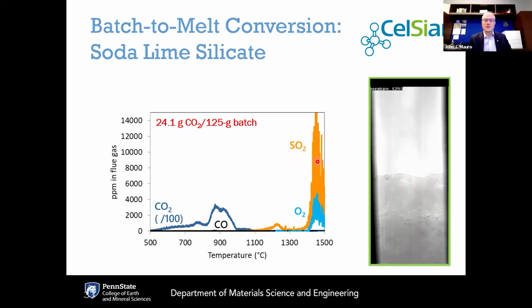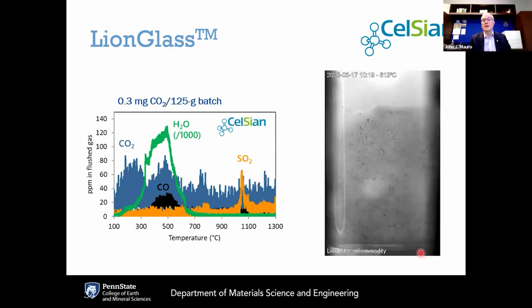The SO2 blisters are just because sodium sulfate is being used as a fining agent. This helps to make larger bubbles so they can get out of the melt faster. By the time you get to 1400 degrees C, this foaming behavior starts, as the fining agent releases sulfate blisters. Then as you get to 1500 degrees C, the foam calms down, the fining process is completing, and you get a nice homogeneous melt that is bubble free. But it really does take those high temperatures to make this happen.